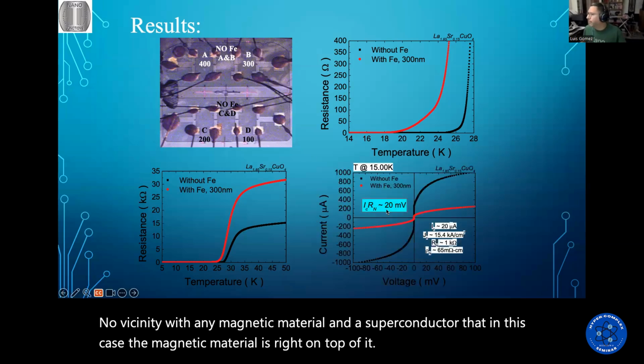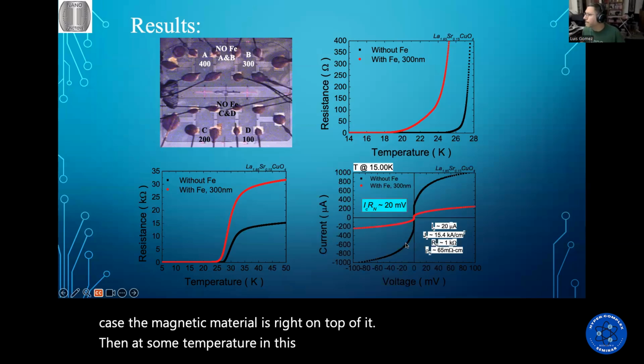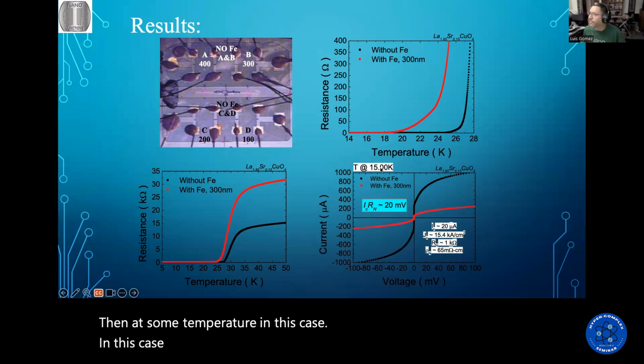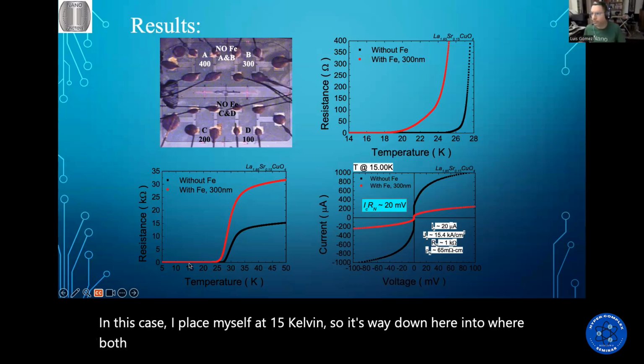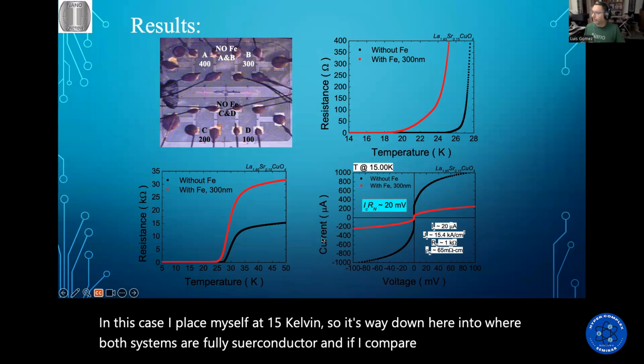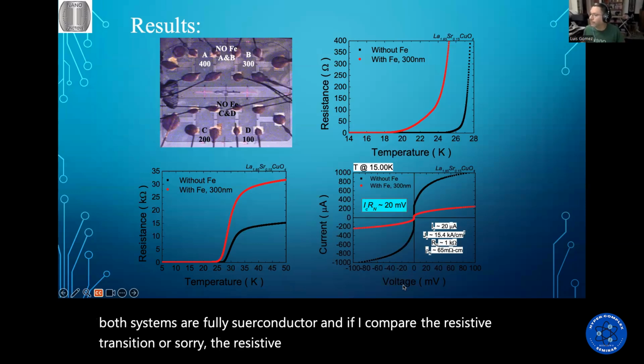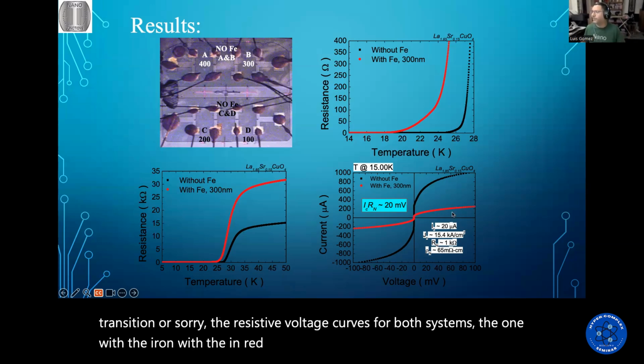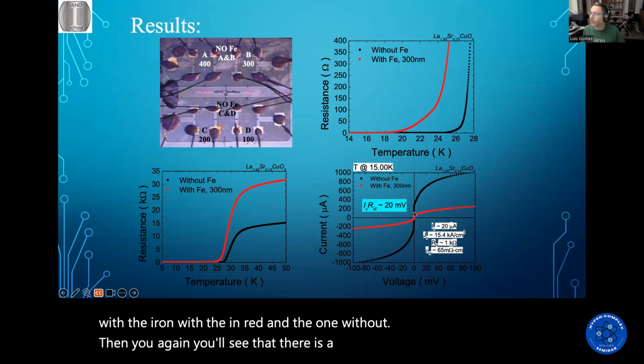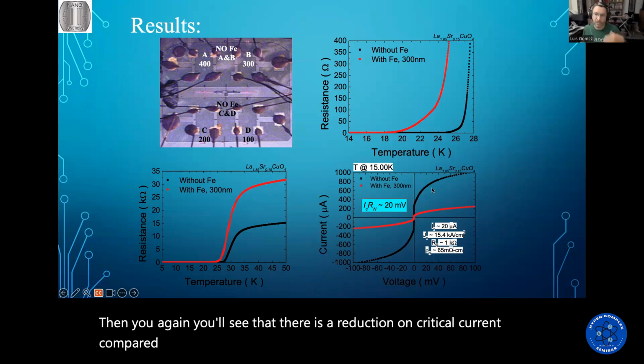Then, at some temperature, in this case I place myself at 15 Kelvin, so it's way down here where both systems are fully superconducting. And if I compare the resistive voltage curves for both systems, the one with the iron in red and the one without, then you'll see that there is a reduction in critical current compared to the virgin film.